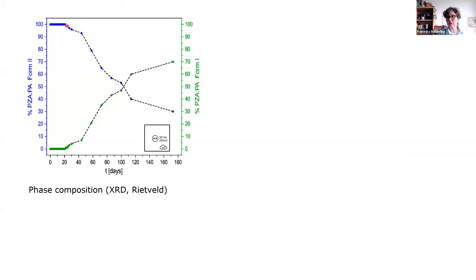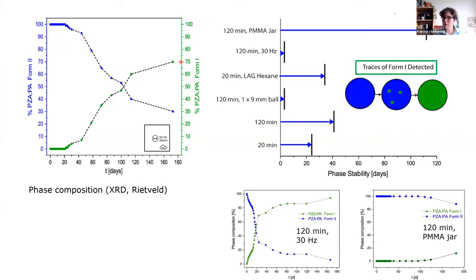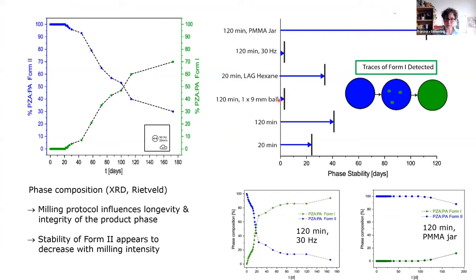So we get a change from the less stable polymorph towards the more stable polymorph here, and the amount increases. We did some tests changing the frequency and also the size of the milling balls used, and here you can see an interesting effect. This is the example I just showed. If we decrease the frequency shown here, and if we decrease the ball size, this is a 9 millimeter ball in the end, then we really have lesser time stable this polymorph two. So the impact the sample sees during the synthesis has a decisive effect on the longevity of the sample.